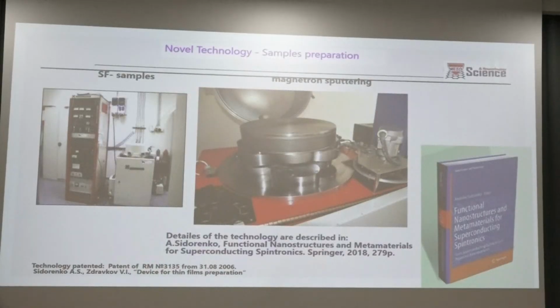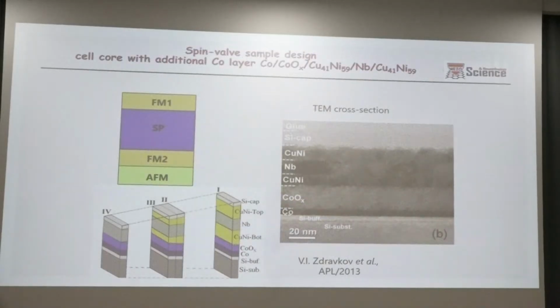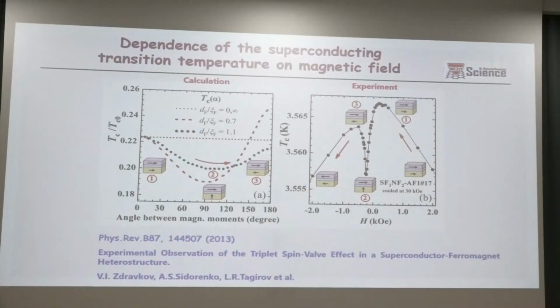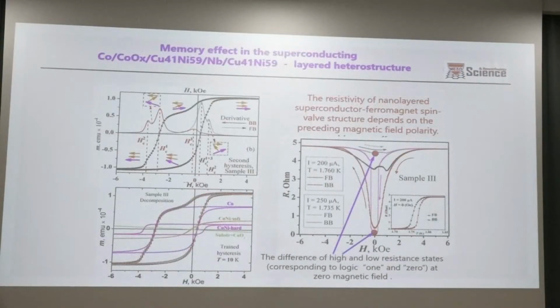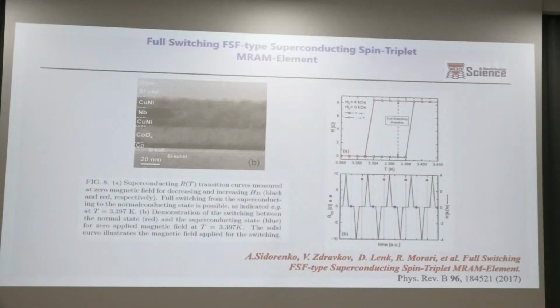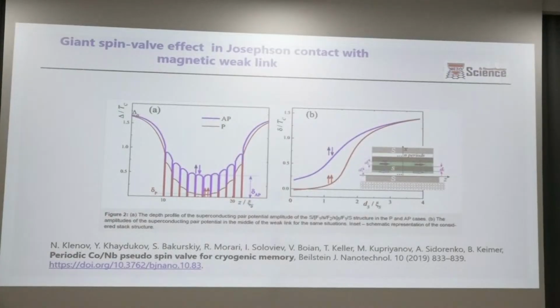And in our laboratory here in Tiginyanu we elaborated such technology, which was patented, and it was described in the Springer book, Functional Structures and Metamaterials for Superconducting Spintronics. And this is the real structure for the triplet spin valve. This characteristic on the left panel is the theoretical behavior of how the critical temperature depends on the mutual magnetization of two layers in the triplet region. On the right-hand side, one can see that there is really an absolute minimum at non-collinear magnetization of the two layers. And here one can see the switching characteristics of such an element.